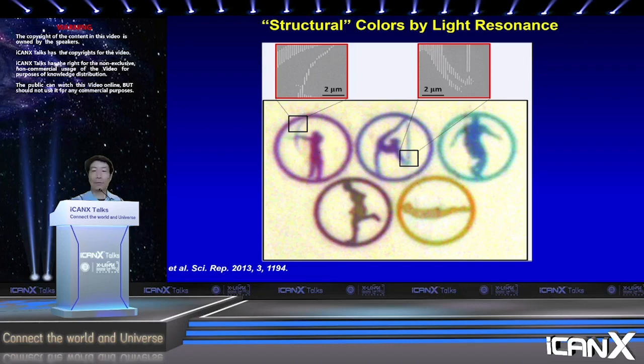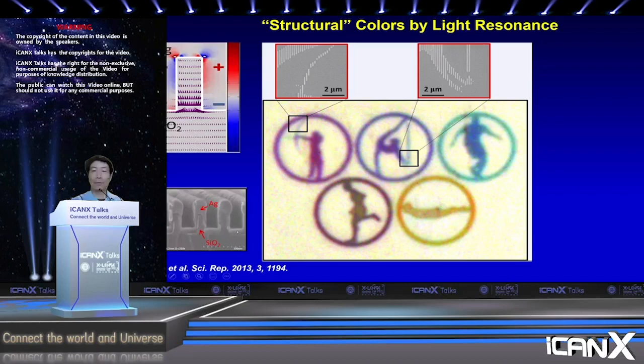So the way to do it is actually quite simple. You take a piece of glass on the lower left, right? You basically etch these nanoscale walls into the glass. And then you just coat everything with a metal, in this case a silver layer. So the light comes from the backside. This is a reflecting color. So whatever the wavelength of light that fits in this nano cavity can create a resonance and eventually get absorbed. And so the color you see is the complementary to the wavelength that is actually trapped in this cavity.